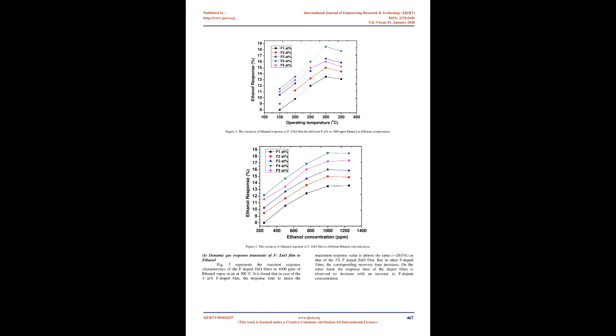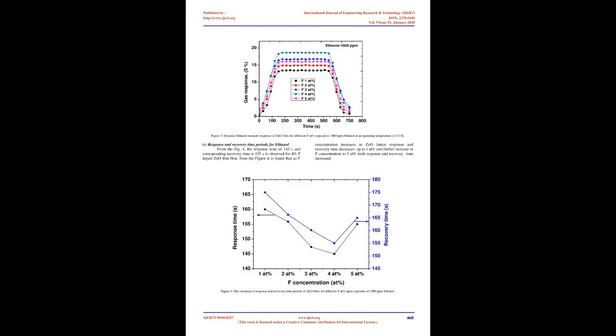3. Results and discussions. A. Effect of temperature and ethanol concentration. Fig. 1 represents the sensing characteristics of the F-doped ZnO films as a function of the operating temperature for 1000 ppm concentration of ethanol in air. It is observed that the F-dopant enhances the response of the films to ethanol. Among all the films, the 4% F-doped ZnO film shows the maximum response, 20.5%, at 300 °C to 1000 ppm of ethanol in air.